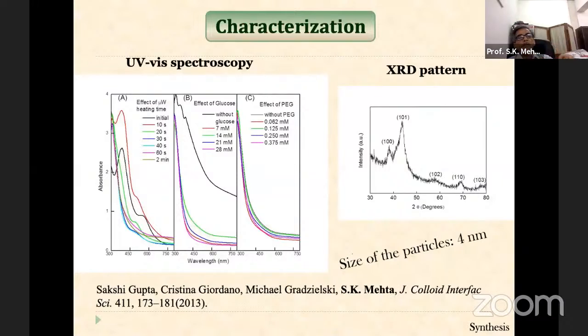So you can see the effect of microwave heating time, the effect of glucose, the effect of PEG. All these variations are done. You want to optimize your system for getting the best information: how much time it will take, the minimum time required for getting good particles, and how much glucose is required. We have varied glucose from 7 millimole to 28 millimole, and PEG from 0.062 millimole to 0.375, and we can optimize this very well.